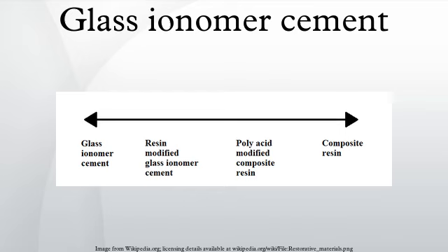Clinical trials investigating the longevity of glass ionomer restorations in primary molars are mostly short-term studies of less than 3 years. The longest survival rates for glass ionomer restorations are in low-stress areas such as Class III and Class V restorations. In an early study, Frencken and others reported that 75% of conventional glass ionomer restorations in primary molars were intact after 1 year, and that margin adaptation, contour and surface finish were all satisfactory.